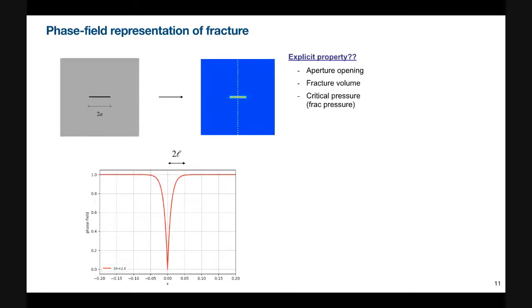So how is the fracture represented with phase field? If we have a sharp line crack like this, then this is a phase field representation of the crack. And if we look at the phase field profile along this scan line, this is how it looks. The phase field variable is one away from the crack, and it's zero at the crack. And then there's some transition zone where the phase field variable changes from zero to one. This transition length is controlled by the regularization length.